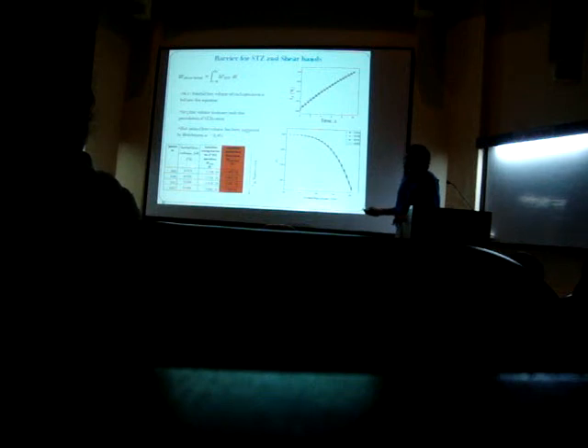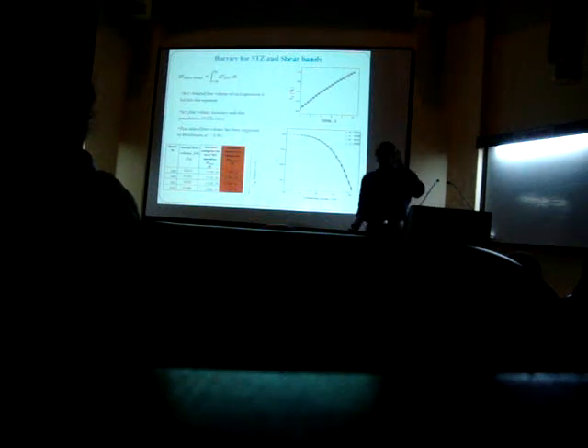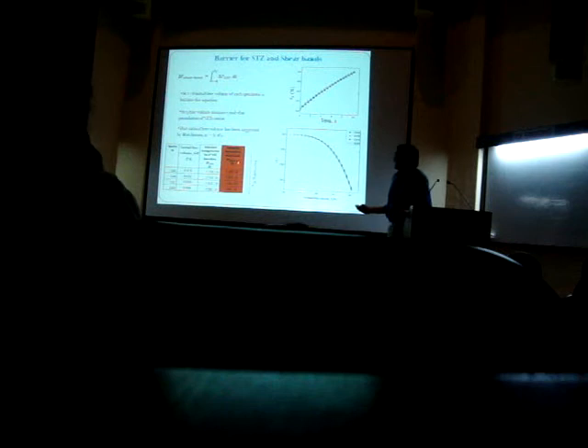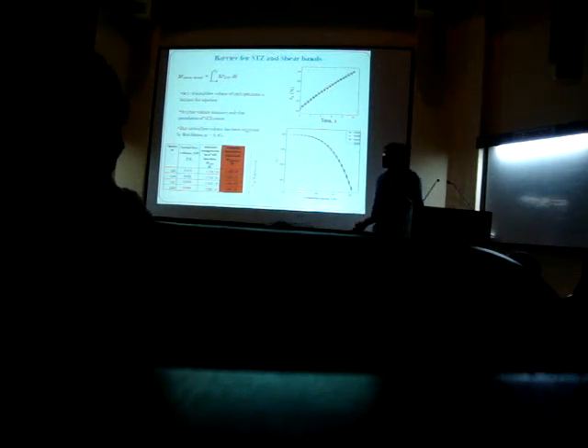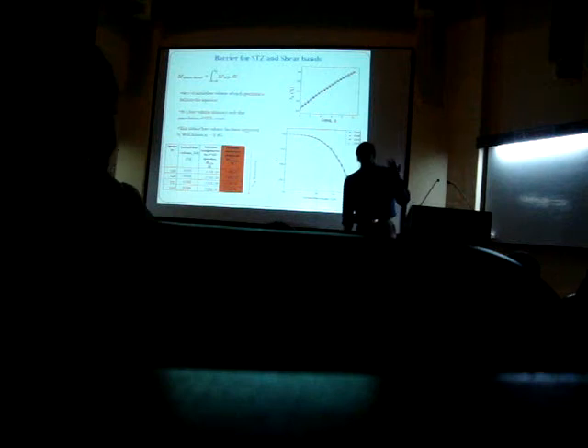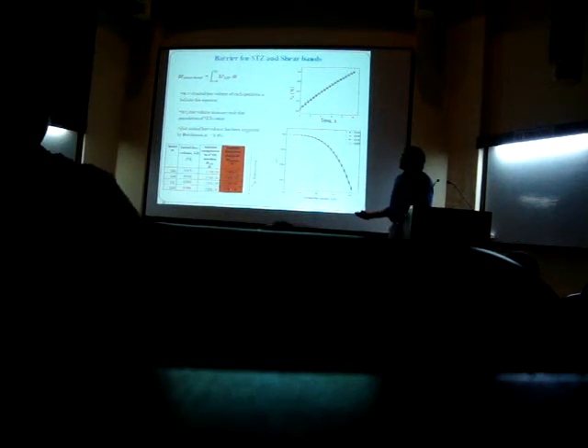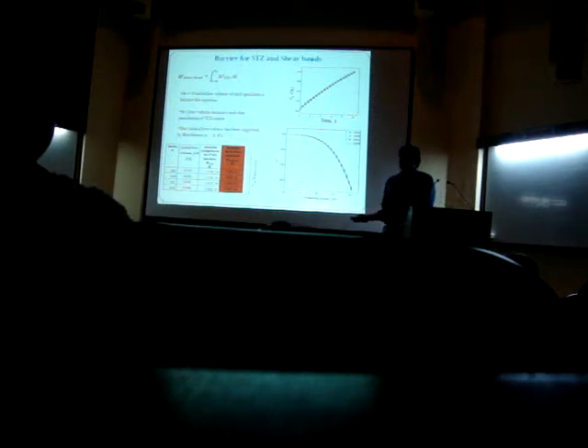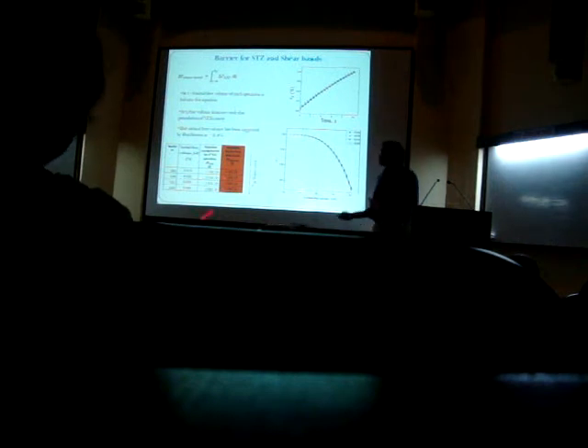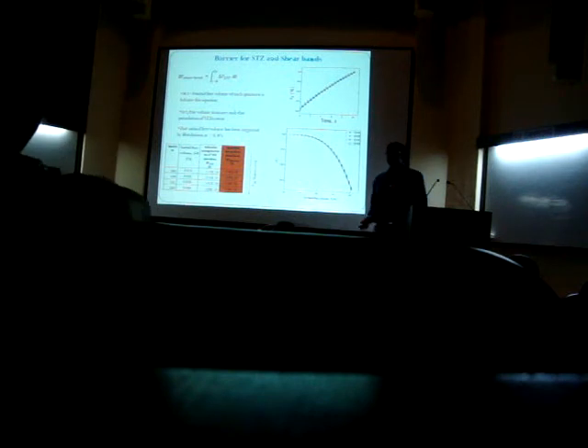And we found that although the initial activation energy barrier for STZ operation on the glasses are very similar, as your shear band forms, the alloy which has got the highest temperature of annealing, or rather the alloy which has got the highest initial free volume, has the lowest barrier for activation of the shear band, which is what matters. And this is why, because of higher free volume, you have higher propensity for shear banding and hence higher fracture toughness.